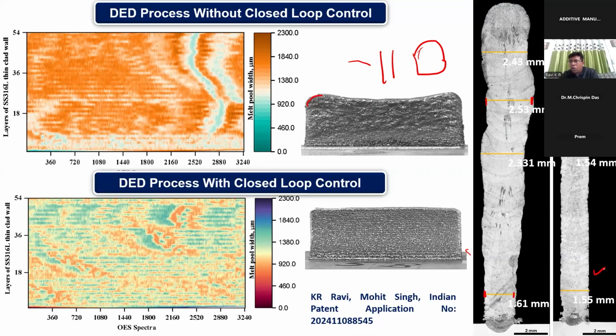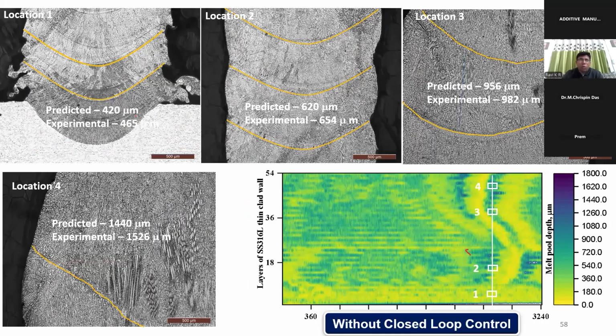On the other hand, if I do closed loop control, you are able to get, throughout the whole part, this is a 54 layer build, consistent melt pool width in all the layers. Not only melt pool width, you can see here melt pool depth.